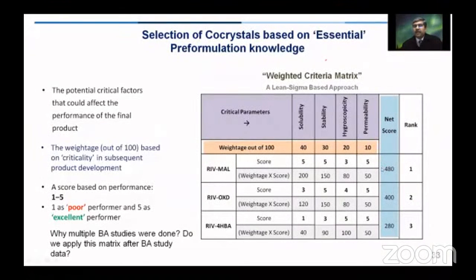We ended up with a net score of 480 for the malonic acid co-crystal, while it was 400 and 280 for oxalic acid and 4-HBA co-crystal. And the rank ordering of these co-crystal candidates with respect to their optimum nature for further dosage form development was: the first rank was obtained by malonic acid, the second one by oxalic acid co-crystal, and the third one with 4-HBA co-crystal.